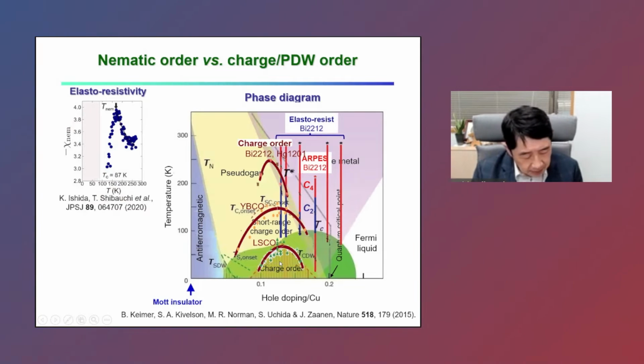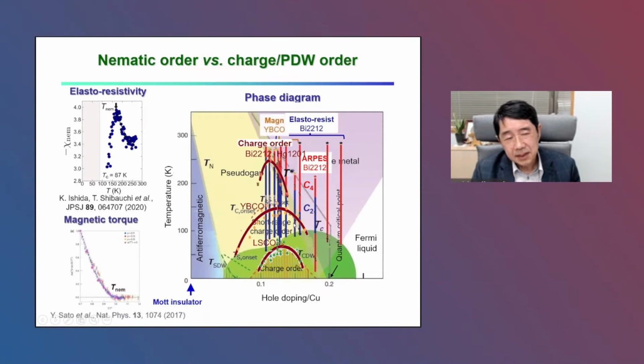So far, there are a lot of other measurements, elastoresistivity measurements. I will not explain in detail, but from these measurements, electronic anisotropy is induced in this blue region. And this is magneto-torque measurements. By torque measurement, one can measure magnetic anisotropy within the plane.